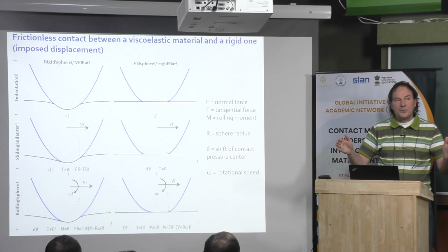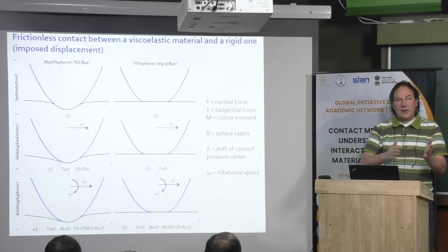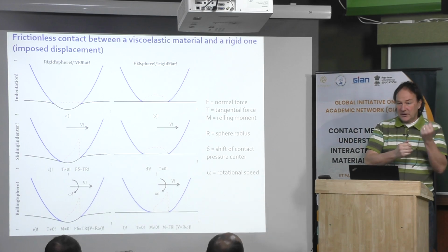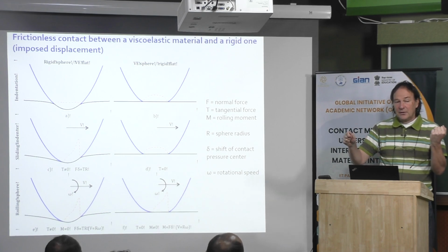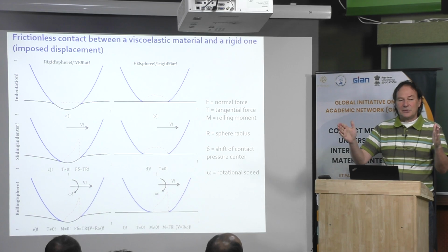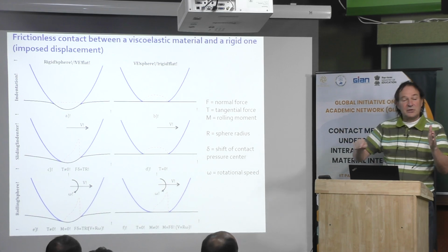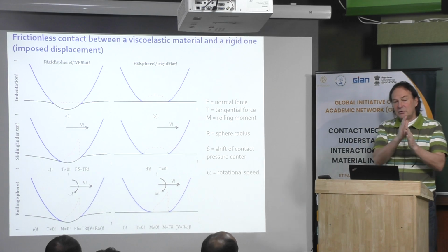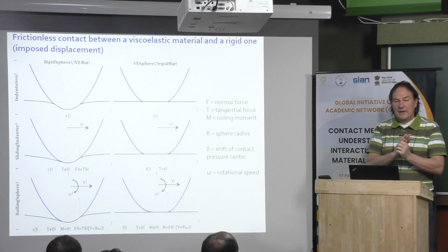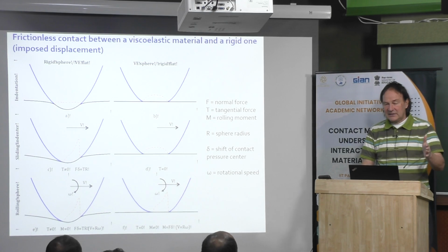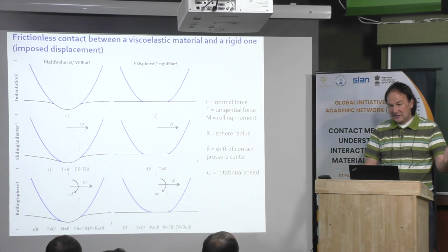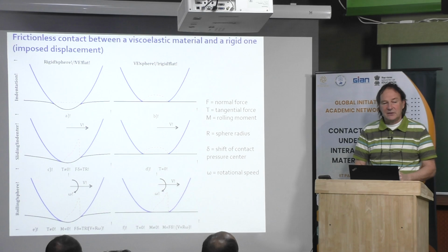In fact, a viscoelastic material, when you have an impact load, is very rigid. When you have a very, very low loading, it's also purely elastic. It is viscoelastic between these two ranges. You have, in fact, a peak of viscoelastic dissipation that can be shifted depending on the frequency. At a very high frequency, it's elastic. At a low frequency, it's elastic. And between them, it's viscoelastic.